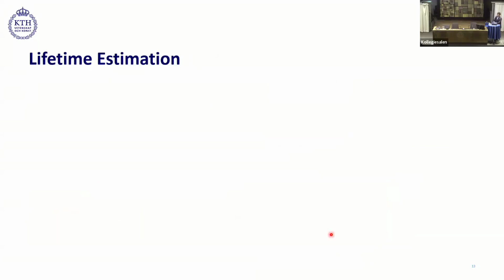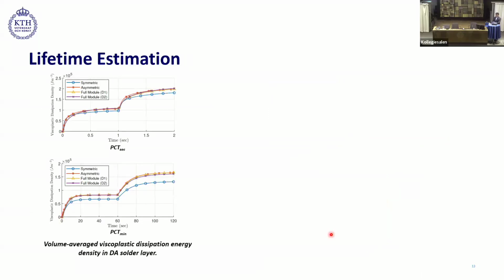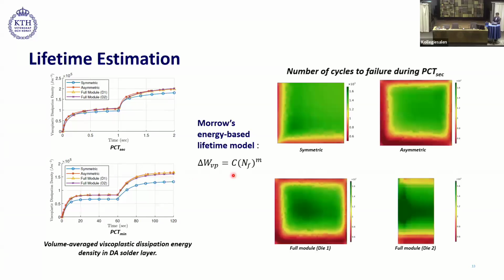We also did a lifetime estimation study using Morrow's energy-based lifetime model. Here, we used viscoplastic dissipation energy density in the die-attached layer to calculate the lifetime of the die-attach. We see here the viscoplastic dissipation density during PCT-SEC and PCT-min. And here we can see that depending on the configuration we have, the dissipation energy density also changes. We feed this dissipation energy density in Morrow's energy-based lifetime model, and then the software gives the lifetime distribution in the die-attached solder layer. We see that in the symmetric condition,